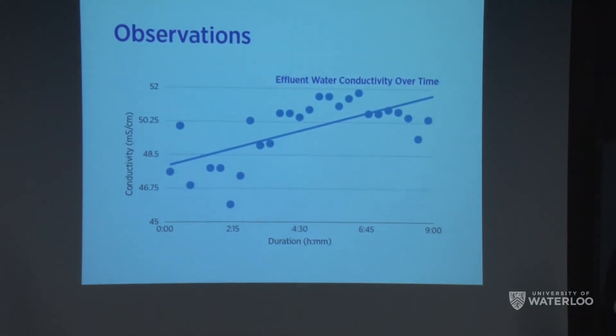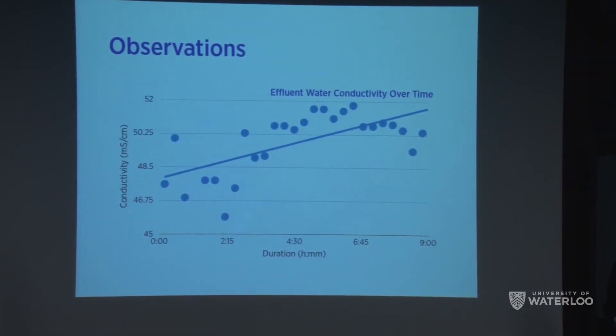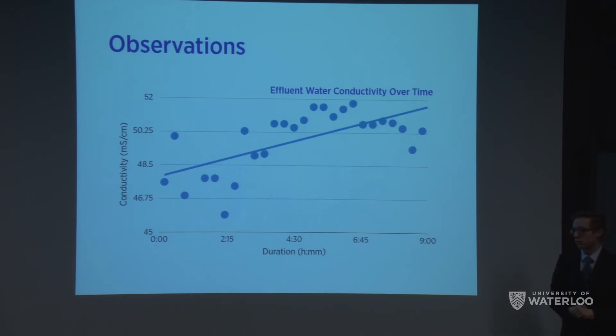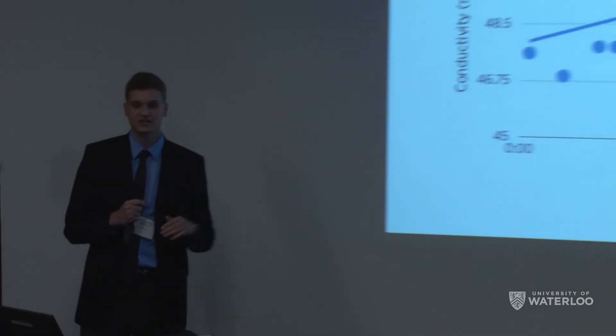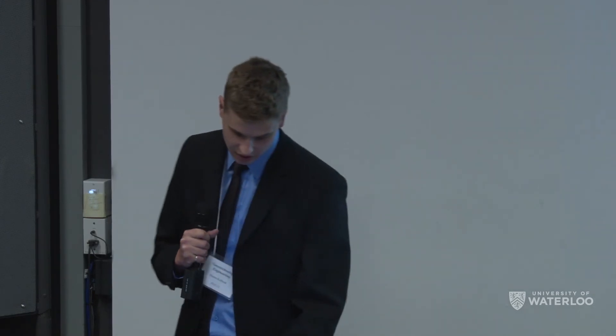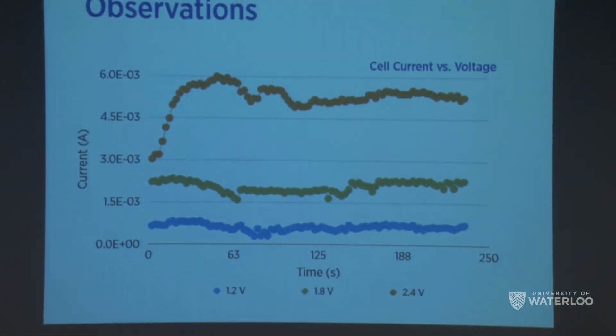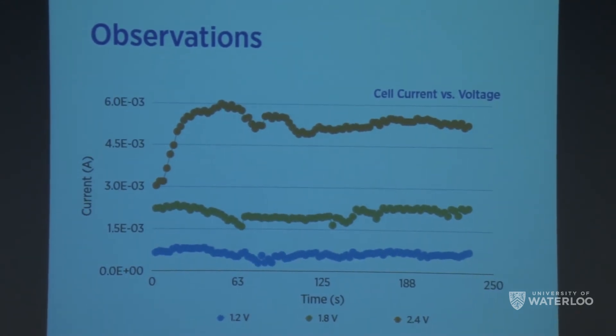With the second iteration created, it was time to start testing. Our first flow-through test didn't show a drastic change outside the error margin of the conductivity probe we were using to measure salinity. We then ran a nine-hour test of the same 110-milliliter, three-gram-per-liter solution — corresponding to brackish water concentration. Far from the expected 40 millisiemens-per-centimeter drop you would expect going from brackish to freshwater concentration, we actually noticed a small uptake of two or three millisiemens. We believe this occurred because the cell was not desalinating and the high-salt electrode slurry was possibly diffusing back over the period of hours. However, the cell still showed something: as we added more voltage, more current was produced, suggesting a faradaic process competing with our desalination attempt.